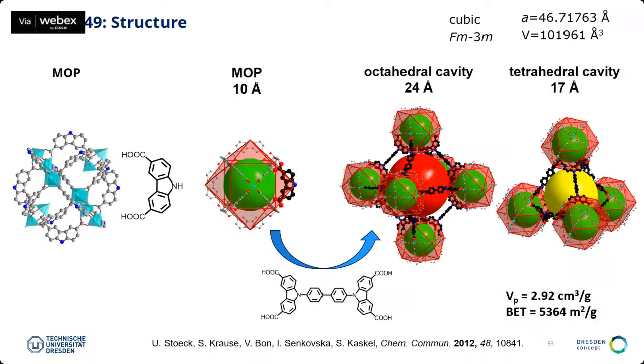Here we are using a bent carboxylate, a carbazole type of carboxylate, which forms a polyhedron. We call these polyhedra MOP. So they have 6 paddle wheels. It's the same paddle wheel unit that you saw before, but now it's copper, not nickel inside, copper 2+. And we form these metal organic polyhedra. And the student Uli Stöck had the idea to connect these polyhedra with a biphenyl strut to make this very porous structure, which has octahedral cavities and also tetrahedral cavities.